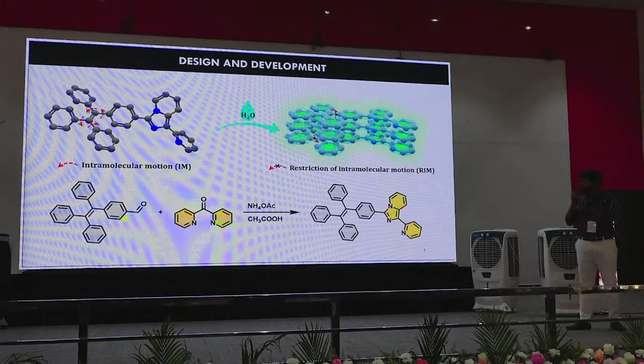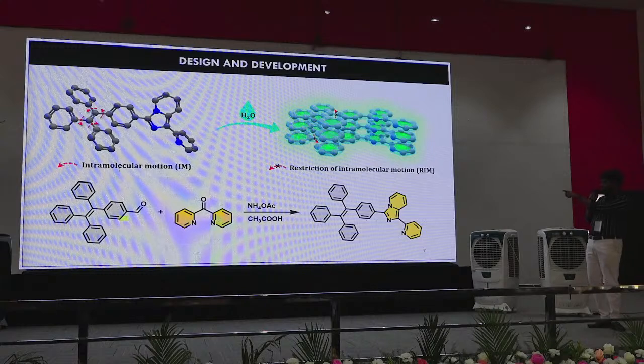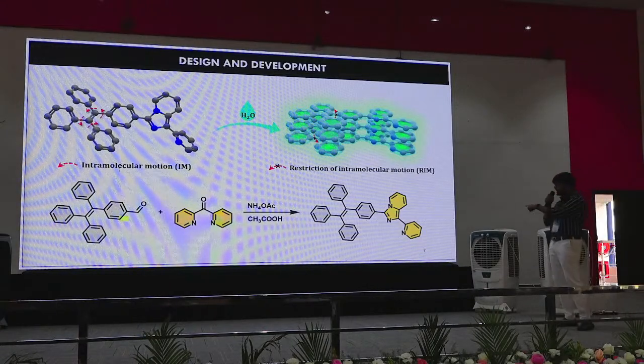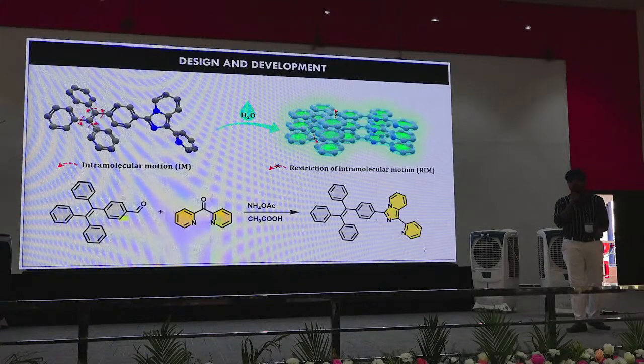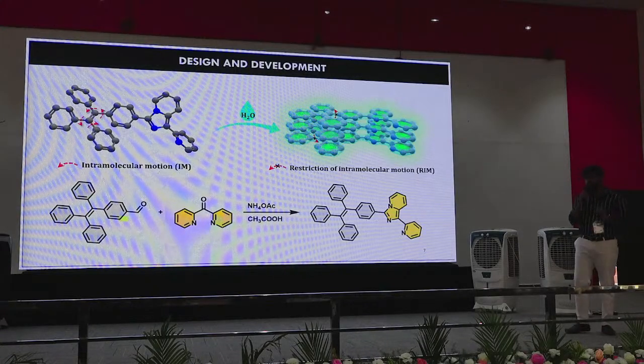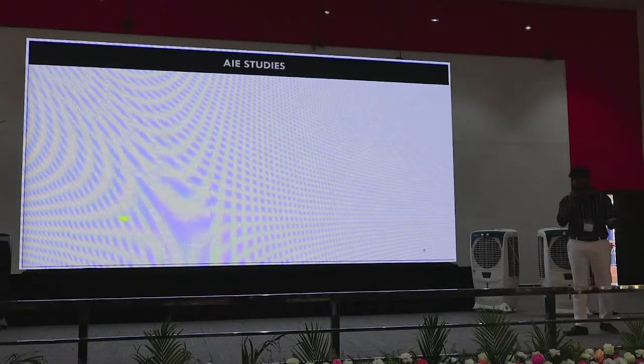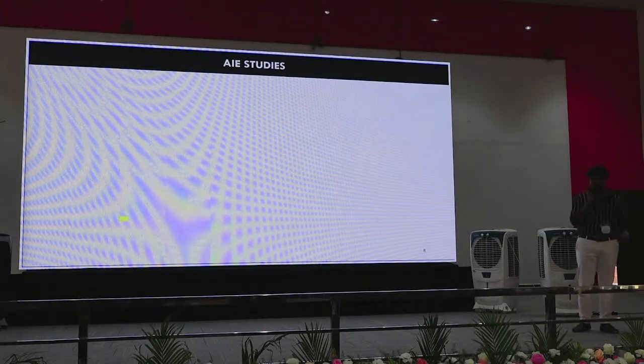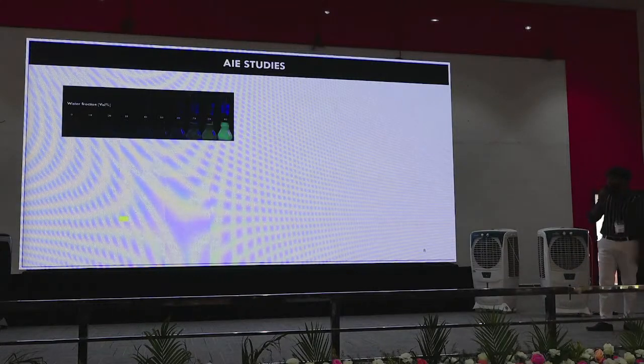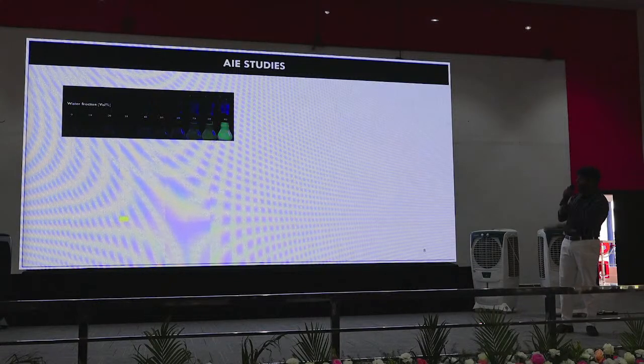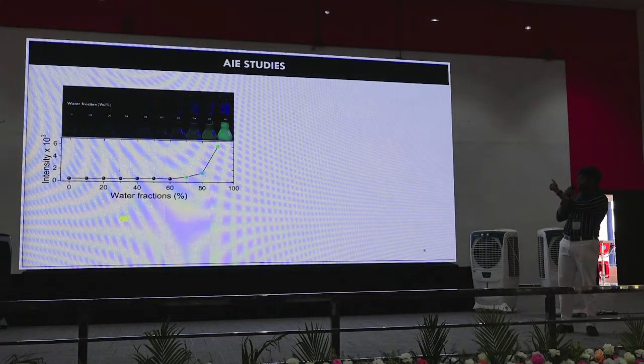So this is the scheme that we have used. We have used a TPE aldehyde, and this receptor site has been specifically designed by our group, which is highly selective for copper. For copper, our group has already published an analytical chemistry, dyes and pigments paper using this receptor. When we vary the water percentage, as you can see visually, at 90% the aggregates are highly emissive.